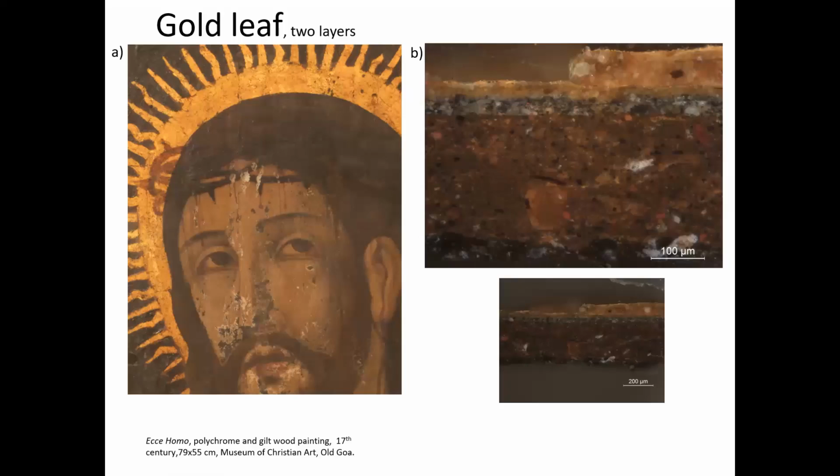Iron oxide as hematite and goethite, also with grains of carbon black, were found in the composition of these ground layers. By microspectroscopy, oil and oxalates were also found in the constitution of this layer.